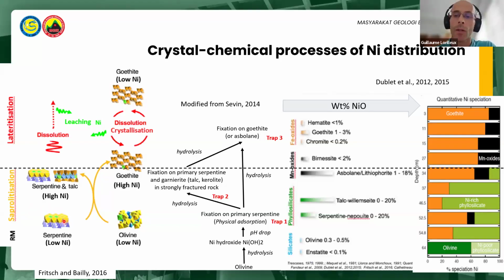During weathering, nickel is released from olivine and fixed on primary serpentine by physical adsorption and hydrolysis. Nickel is also leached from olivine and primary serpentine and fixed on hydrous magnesium phyllosilicates, and subordinately by oxides such as goethite in the saprock. This trend is reversed in earthy saprolite, where goethite is the main carrier, with some residual phyllosilicates still detected. These hydrous magnesium silicates consist of neoformed garnierite and of secondary nickel-enriched early serpentine.